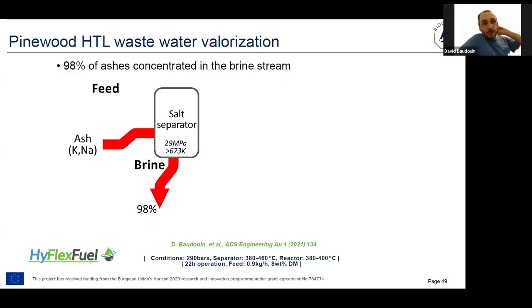So in the salt separation in this project, at least with some of the streams tested, we were able to have a very good recovery of the salt, so extraction of the salts. You can see here the mass balance was very high, up to 98%.